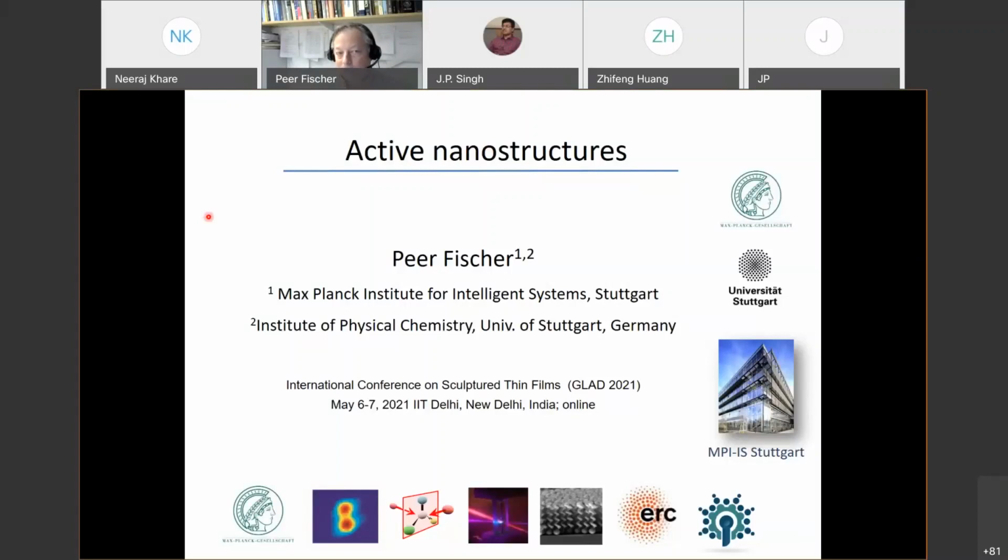Yeah, this is known. This is what people have studied a lot. Titanium dioxide is a really much studied system. If you add metals, it somehow brings the Fermi levels a little bit closer, and one believes that there is hot electron injection. So you basically have this antenna effect and absorption of light, and then it can inject more effectively into titanium dioxide. And then you can use visible light, also green light, to excite these structures.